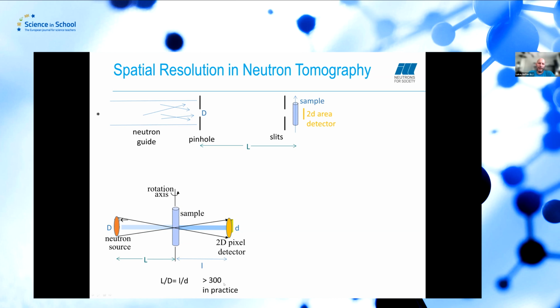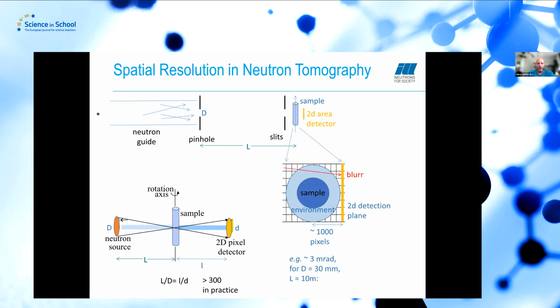And that means, in practice, in order not to sacrifice too much neutron flux, because if you close the D, the large D, capital D, then the neutron flux goes down, so in practice you're staying in something like 300, 600, whatever, in order to get enough collimation. Of course, it depends on afterwards how close we can go with the detection plane towards the sample.